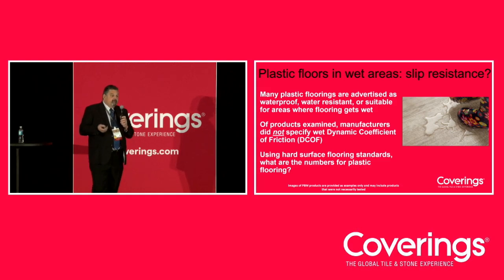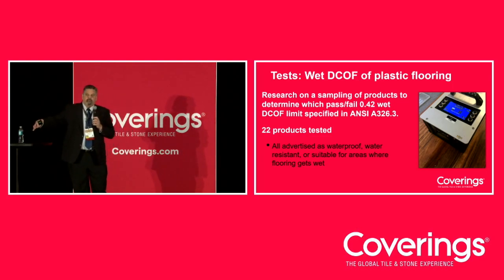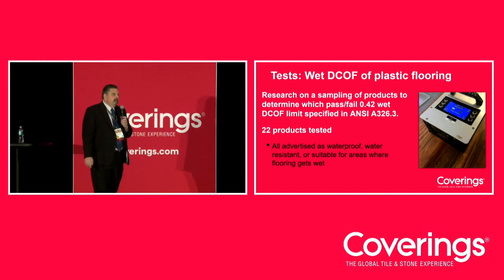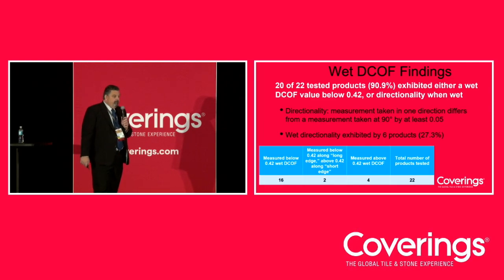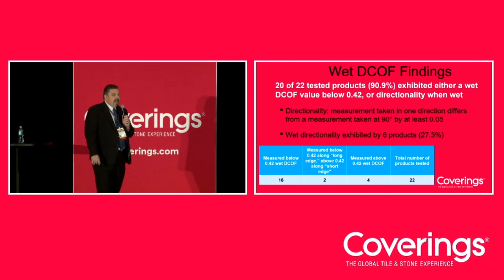So we used our test equipment. This is the BOT 3000, which runs across the floor, and it measures how much resistance there is to moving across the floor, and that's your coefficient of friction. 22 products were tested. They were all advertised as being usable in wet areas. Of those, 20 of them, the ceramic tile industry would not have told you to use in a wet area because they weren't 0.42 DCOF or higher. They were, in some cases, quite a bit less than that.